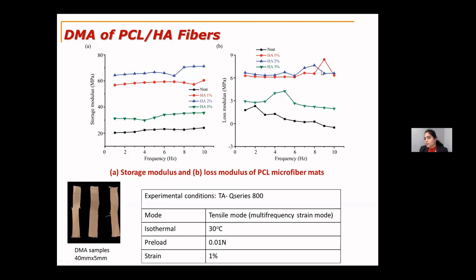And the same goes for the loss modulus. Here also we see that for the 2 weight percent hydroxyapatite, the loss modulus is higher compared to the 1 and 3 weight percentages. So we can see that infusing the nanoparticles into the polycaprolactone solution has definitely increased the thermal stability of the fiber as well as the mechanical strength of the fiber.